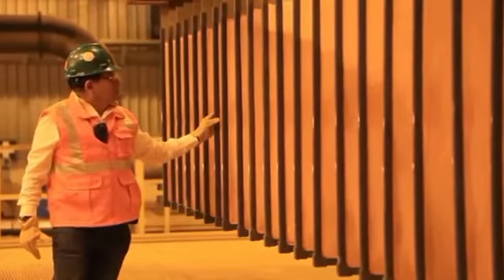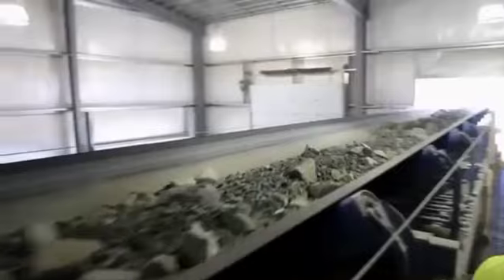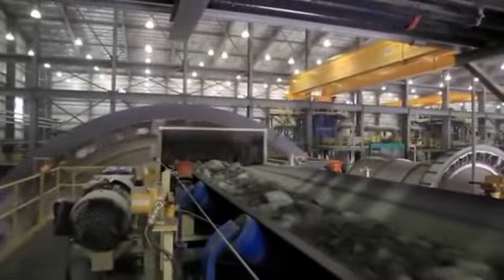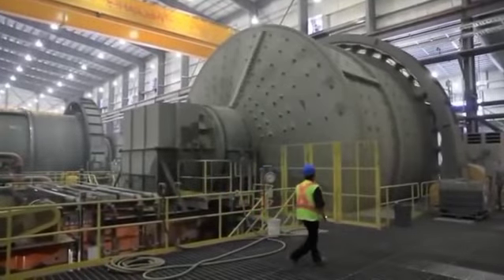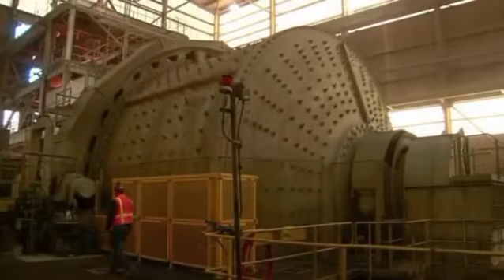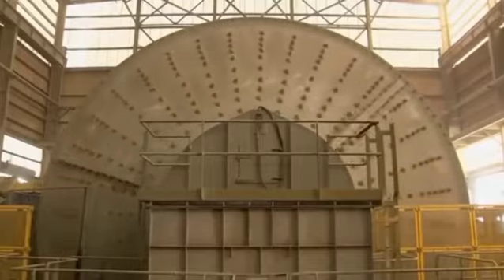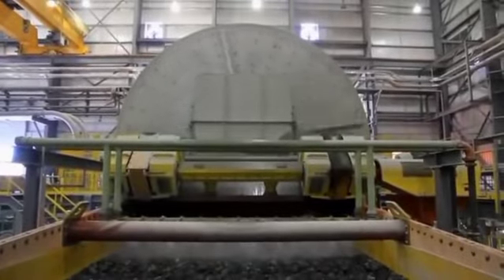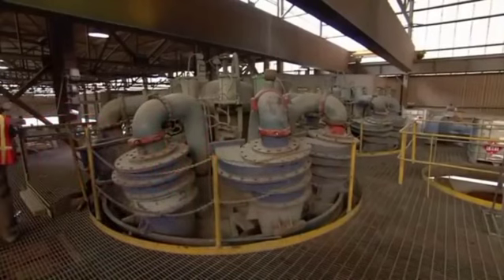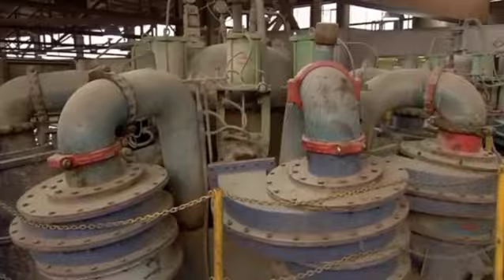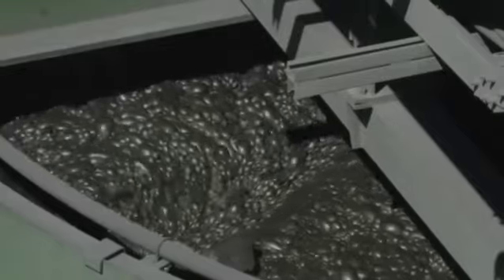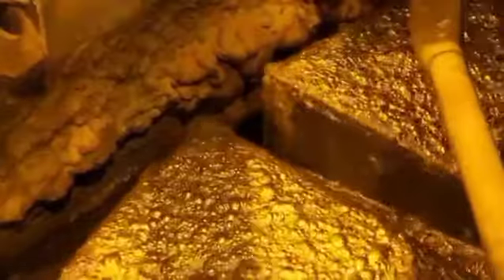In a special channel, the copper solution is combined with an organic reagent and floats to the surface. Then an acidic solution is added to increase the copper concentration and make it electrically conductive. The solution is transferred to a series of tanks containing thin copper plates called cathodes. When an electric current is applied, the copper ions begin to deposit on the plates. In just 10 days, each one reaches a thickness of 2.5 centimeters and a weight of about 125 kilograms. The purity reaches 99.99%, which is essential if the copper is to be used in electrical products.